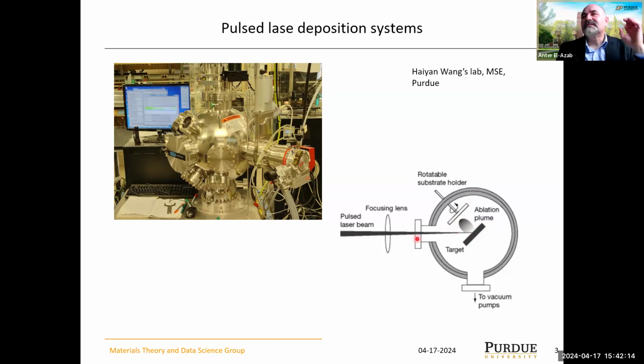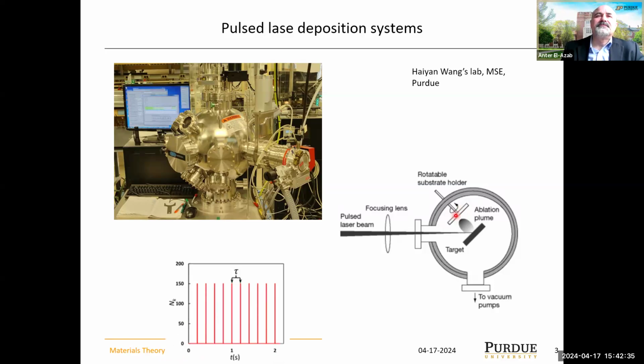Pulsed laser means that we send the energy of the laser in pulses, like 5 pulses per second, 10 pulses per second, and so on. Tailoring the energy and the target material gives a variety of parameters to look at that control the growth of these films, including the substrate temperature as well.